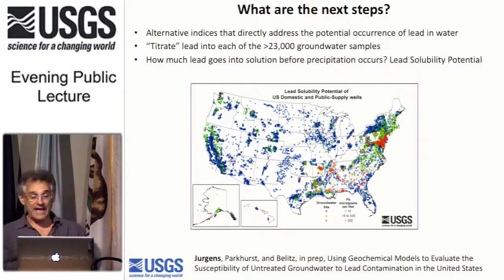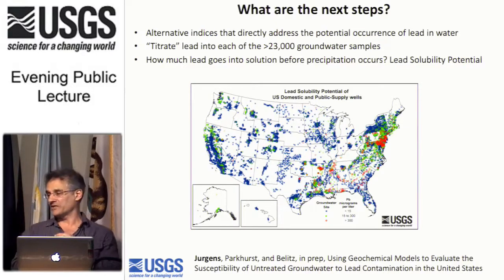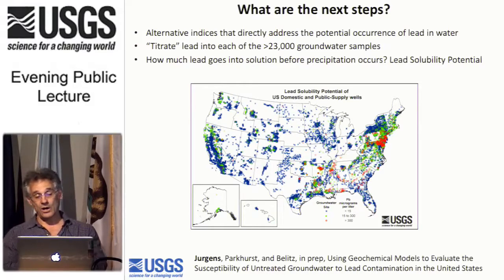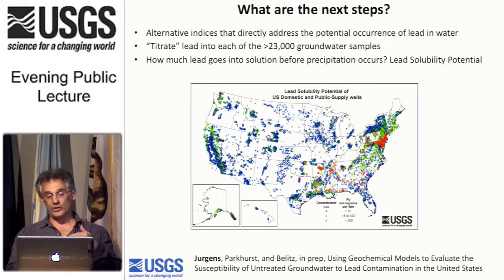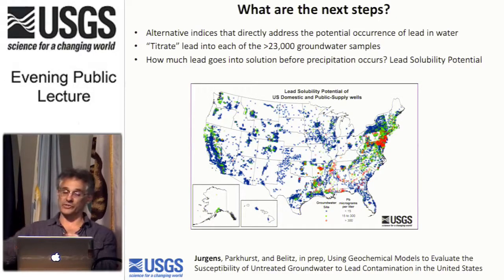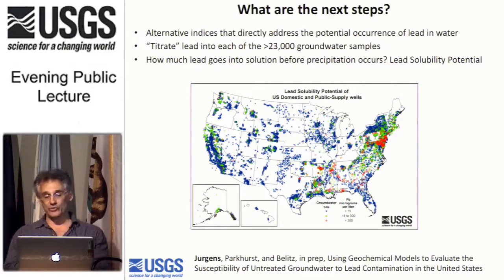So the red values are sort of the top 10% of all the 20,000 plus samples that we have. Those are samples where you have to add 300 micrograms per liter or more before you see any lead precipitate out. So that's 20 times the EPA action level of 15. The green values that you see are samples where you would add somewhere between 15 and 300 micrograms per liter before you see the lead even begin to precipitate. The blue values are those samples where lead begins to precipitate before you have to add 15. So this is a more direct indication.